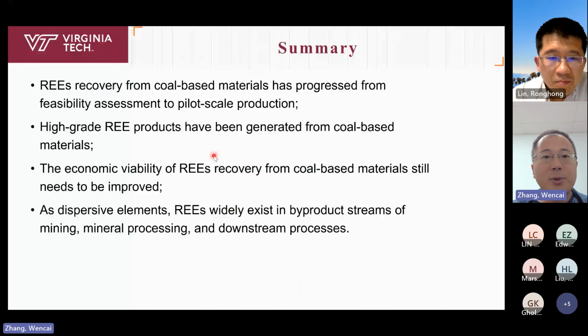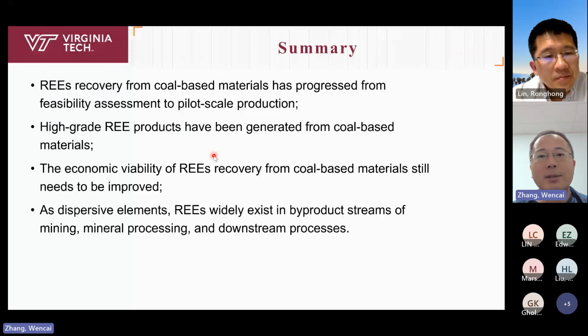In summary, rare earth recovery from coal-based materials has progressed from feasibility assessment to pilot scale production. I know that some teams are trying to build a commercial plant, but I would say that the economic viability of rare earths recovery from coal-based materials still needs to be improved. The major factor is that the rare earths content in coal-based materials is still too low compared with some